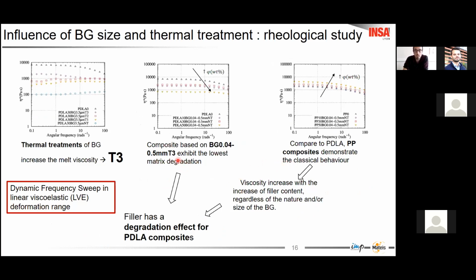So the rheological study can be used as a tool to characterize the effect of bioglass on the matrix. The degradation is related to the loss of viscosity, and here in the first figure, we can see that the bioglass with the thermal treatment T3 has the highest viscosity, and so is the least degraded.